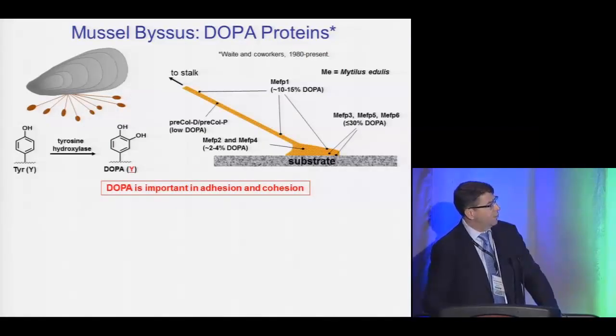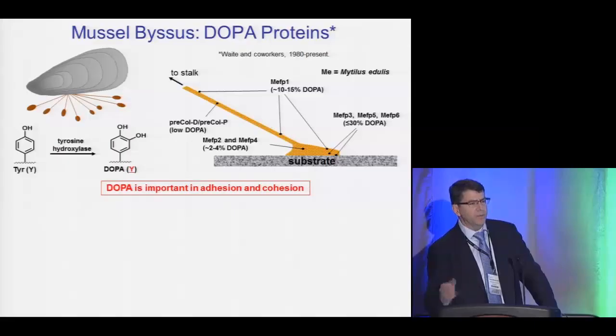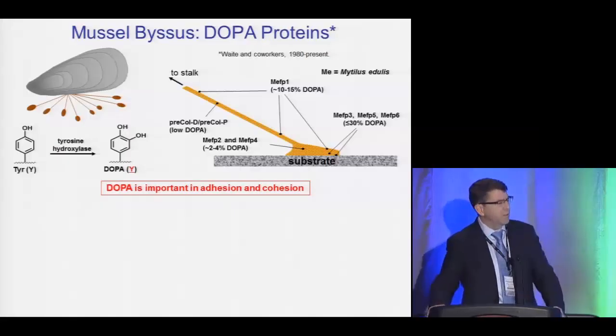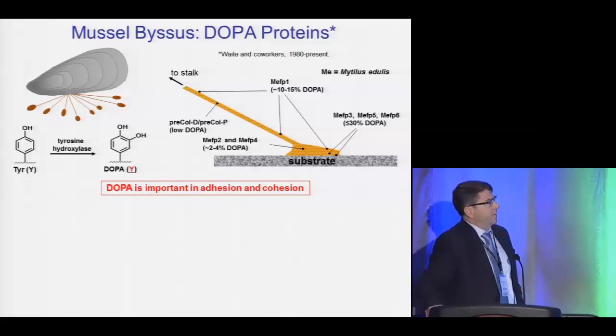And as Kevin mentioned, one of the defining features of these proteins is this amino acid DOPA. It's derived from tyrosine. So the proteins are secreted and post-translationally modified to add this second hydroxyl group. And this side chain is referred to as a catechol functional group. And DOPA is really found throughout that entire byssal structure, including the threads as well as the adhesive pad. Most notably in the proteins that are found at the interface. And those proteins can contain upwards of 25% of DOPA, and DOPA is not incorporated in proteins in high concentrations in any other organisms except for a couple of marine organisms that utilize adhesives. And it's not found in vertebrate proteins anyway.